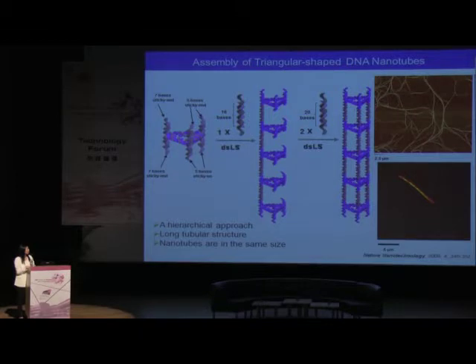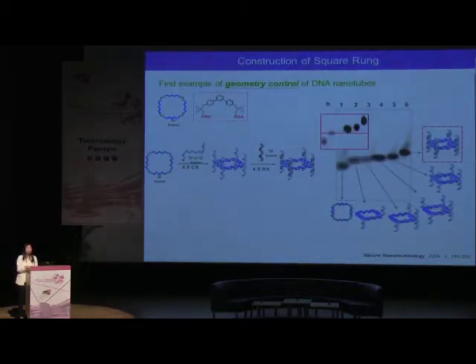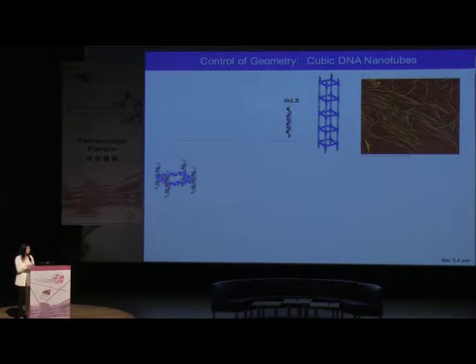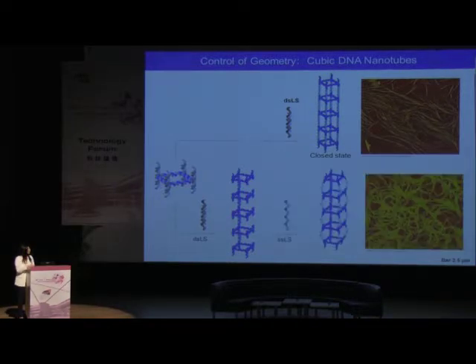And here is just the characterization using the AFM and then the confocal. And you see they are very long tubular structures, and most of them are of the same height and size. So using this approach, besides this triangular-shaped nanotube, we can also generate the square-shaped nanotube from this square template to form the fully double-stranded square DNA nanotube. But the interesting thing here is that we can also generate a less rigid and more flexible nanotube by only adding one double-stranded linking strand here, and the other three sides are single-stranded DNA. So basically, you can see the big difference in their flexibility.